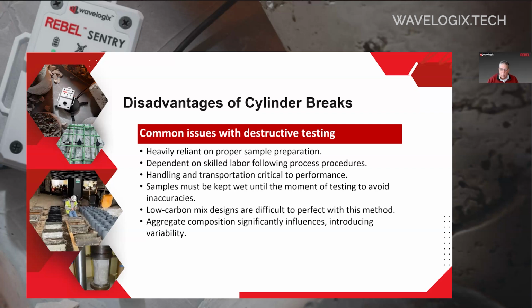More specifically, the disadvantages of using cylinder breaks, which is very common with destructive testing, is they're heavily reliant on proper sample preparation. And we require skilled labor in following those procedures. For those of you who don't know the process in making a cylinder, typically at the end of the truck that's delivering the concrete, when they're dumping out the concrete to be used in the operation, a test technician would take a sample of that, usually in a wheelbarrow of the concrete, and then they would fill up cylinders.